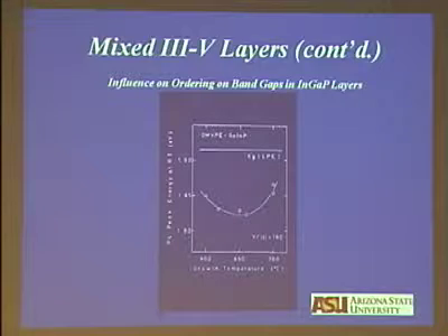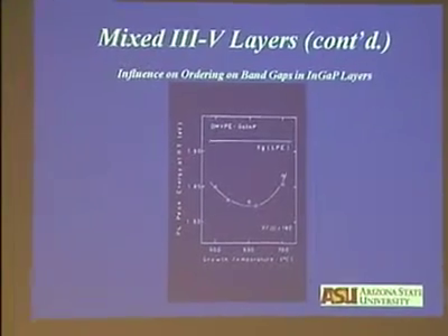So phase separation changes atomic ordering, which lowers the band gap of the material. There is a story: Philips used to make these lasers for disc players, and they did not understand the growth. The band gap is very sensitive to atomic ordering, so they used to get fluctuations in the lasers they were developing. Finally, they went away from the exact orientation and killed atomic ordering, and they were able to produce lasers with a consistent wavelength.